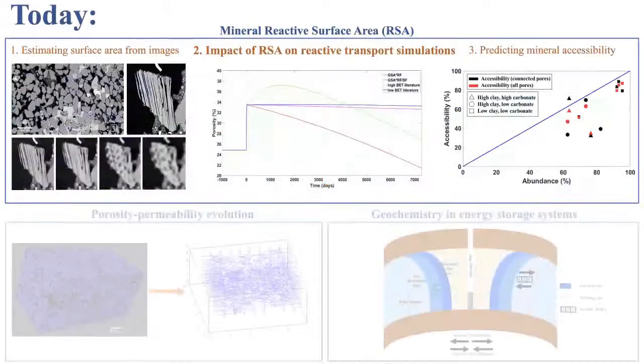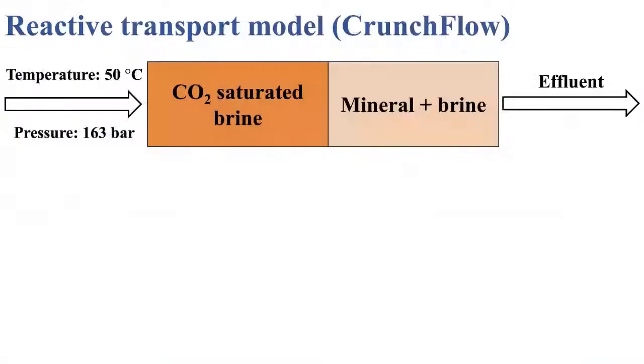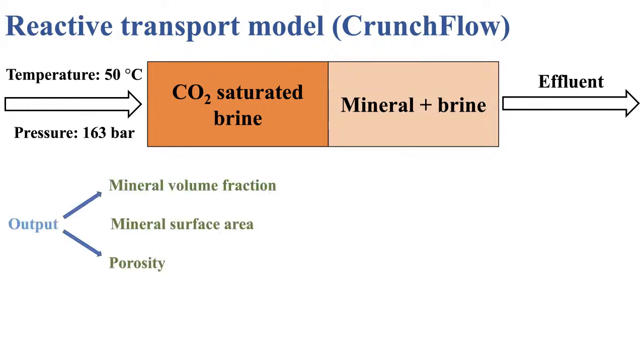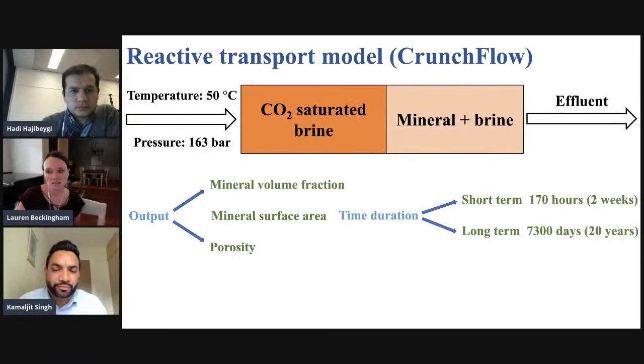And so does this have any impact then on the results of reactive transport simulations if you use this data to construct your model? So here we carried out CrunchFlow simulations at the continuum scale, mimicking the conditions at the site. We tracked the evolution of mineral volume fractions, surface area, and porosity. And we considered 2 time scales, one of a short time scale, about 2 weeks, which is pertinent for a laboratory experiment, and then a long time scale of 20 years, which is more pertinent for the field scale system.